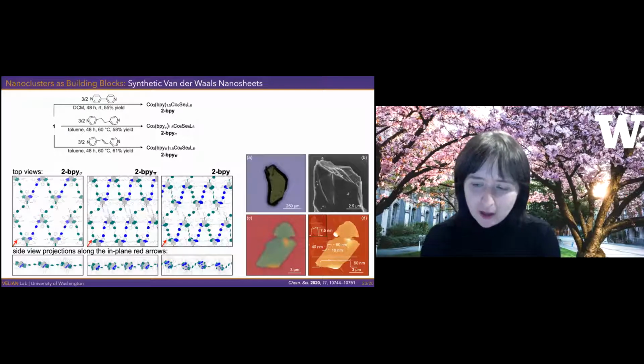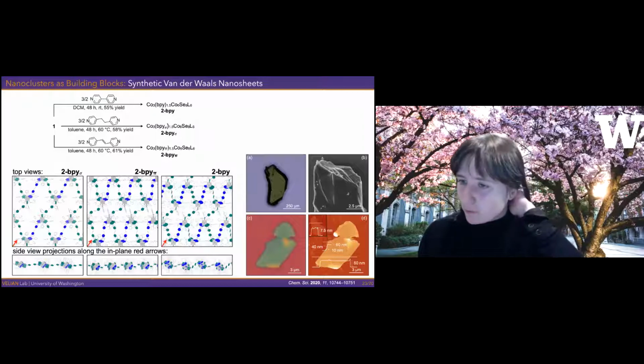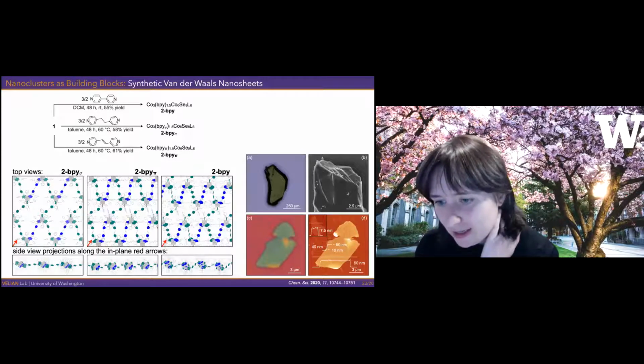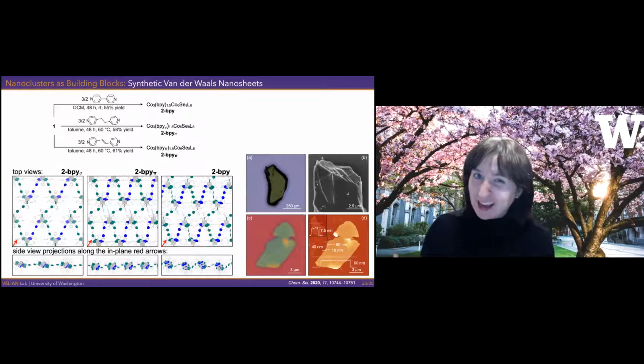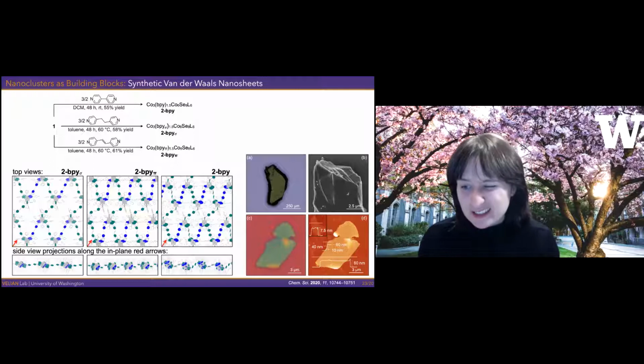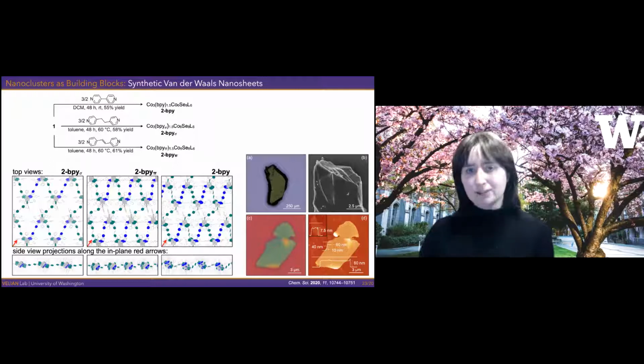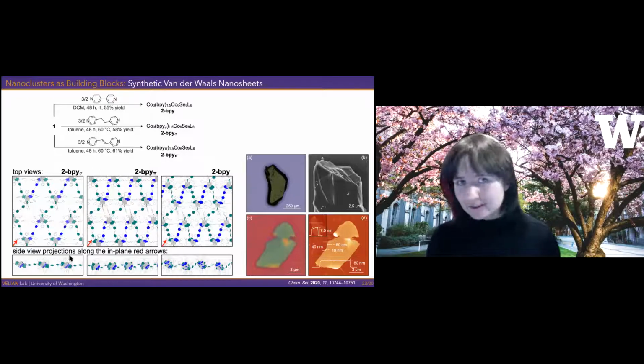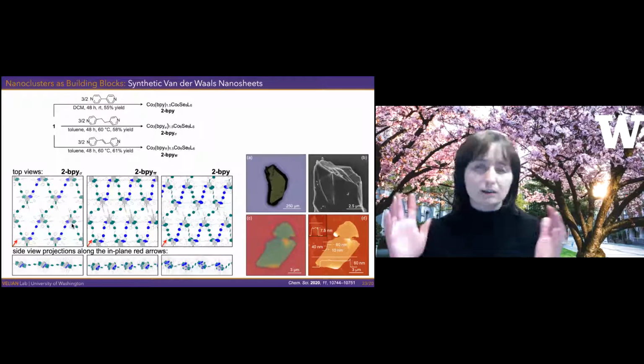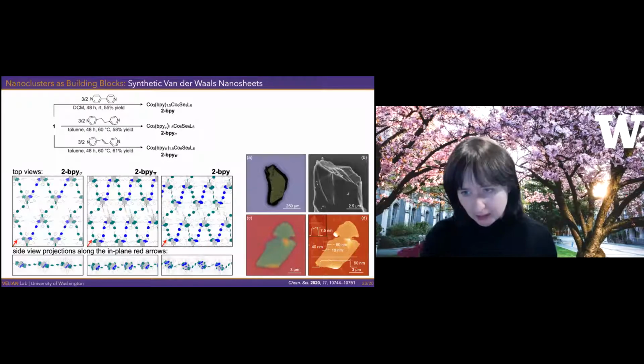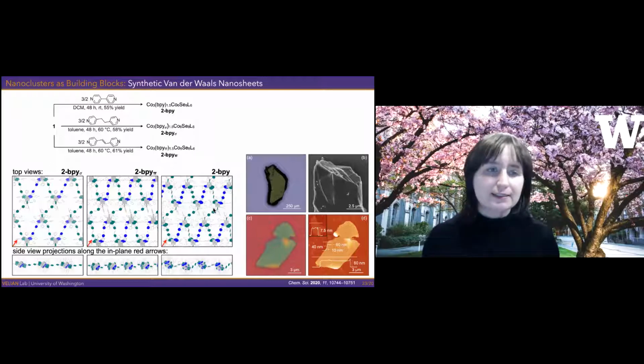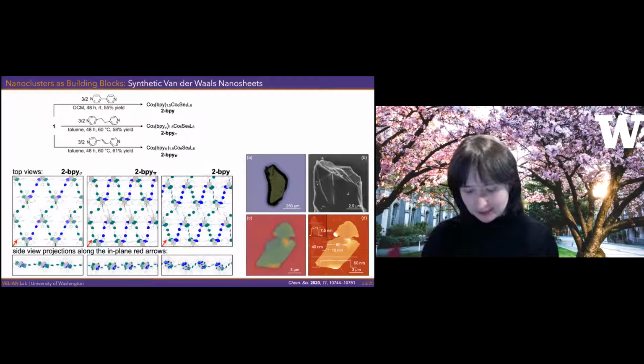What I'm showing you here is how the materials can be characterized by X-ray diffraction, but also, if you look at their morphology, you can see this layered structure. In fact, you can peel them off using mechanical means, like Scotch tape, and then probe them. This is optical microscopy, this is scanning electron microscopy, and this is atomic force microscopy, AFM, on a single flake. After you exfoliate it with the Scotch tape, we can get very thin flakes of these essentially synthetic nanosheets. Think graphene, right, that you peel off. And we'd love to take this to the next step and add functionality to these atomically precise nanomaterials.